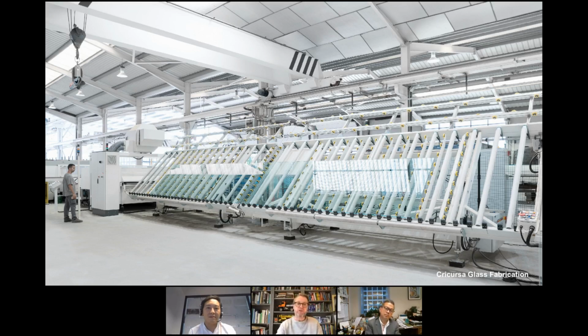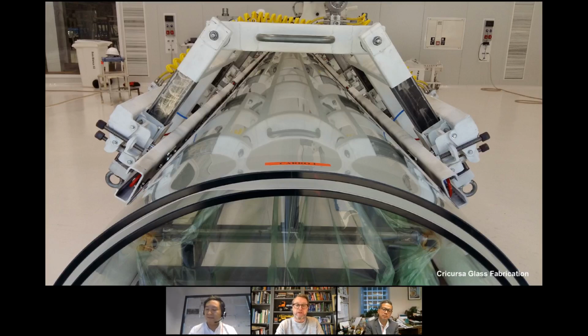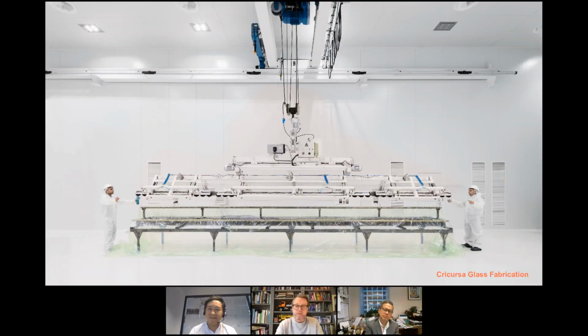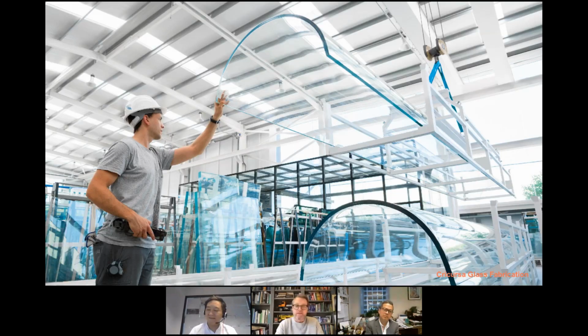So just some shots of Cricursa's facility. Here you can see the flat glass being cut prior to its bending process and its slumping. After it's been slumped through the oven, you can see here these two half tubes nestled one on top of each other, and you can just about see the plastic layer between the two, which is the interlayer, before it's then put into the autoclave and heated under pressure in order that the two pieces of glass would bond together. This is the preparation of that.